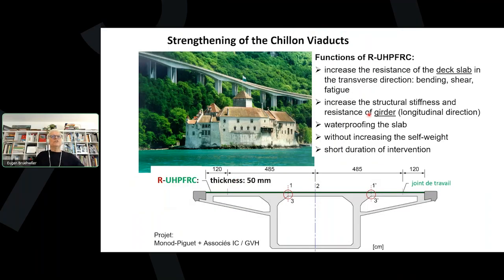Actually, initially, the engineers designed using so-called traditional methods to strengthen this viaduct, but then they found out it's very expensive, and they came and were asking whether UHPFRC is a method, and together we developed this concept, which is very simple. So we have a layer of UHPFRC of 50 millimeter thickness on top of the existing reinforced or post-tension concrete slab.